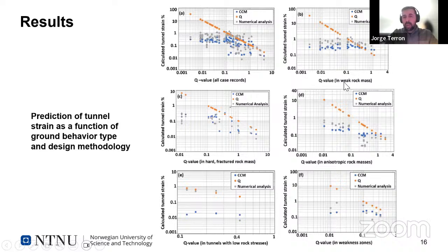When we move on to weak rock masses, for example in large fault zones in Norway, there is also a good correlation down to 0.1, but below 0.1 there is a bad correlation. However, it is not the same as when we plot all the cases, because when we reach Q about 0.6, 0.7, this agreement or overlap is missing. So there is, in fact, a difference in the behavior and also in the performance of those design methodologies in how they capture or prognose tunnel deformation.